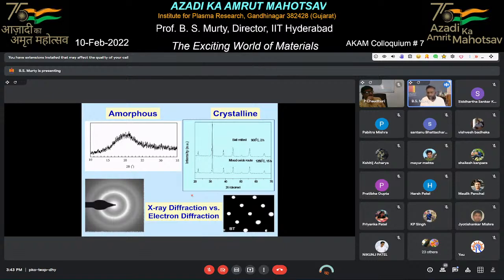Crystalline materials are those where you have a three-dimensional periodicity along with a local rotational symmetry. So they said a material to be called crystalline should have both rotational symmetry and translational symmetry. And such a crystalline material, if you subject it to X-ray diffraction, you get peaks like this. By looking at the peaks, we can find out the crystal structure to some extent. Some calculations have to be done, but one can do this.